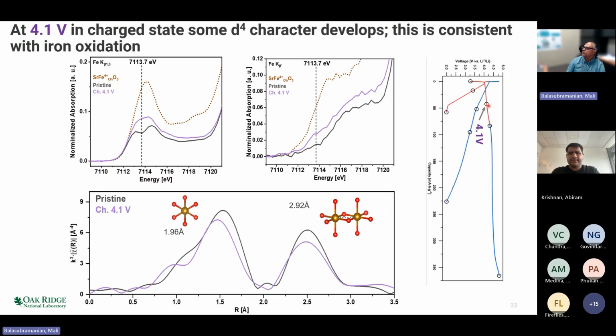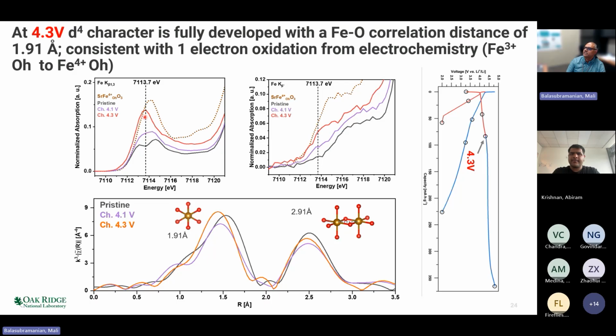Now, if you charge it to 4.1 volts, you reach here. You see that the doublet nature changes a little bit in the K beta 1,3, and a nice sharp feature starts coming here in the K beta prime. So this clearly shows that you are starting to have iron in a 4 plus state as you go to 4.1 volts, and the bond distance shrinks as should be expected for an oxidized iron. You go to 4.3 volts, this peak increases, and then you can see that this feature also increases, and we believe that you have fully developed an iron-oxygen correlation distance of 1.91, and this represents a 1 electron oxidation of the iron 3 plus to 4 plus, as can be viewed by this increased intensity at 4.3 volt.